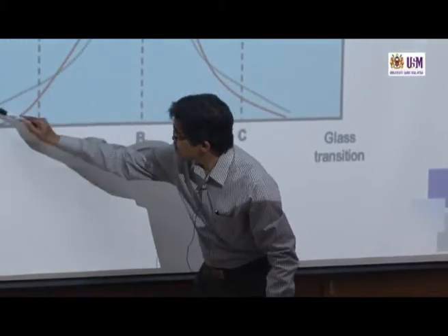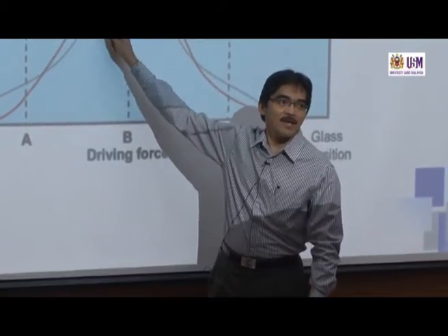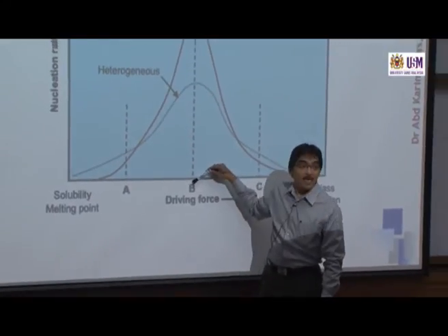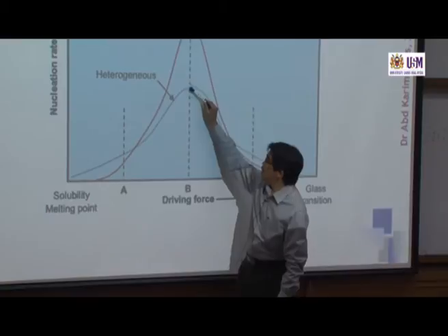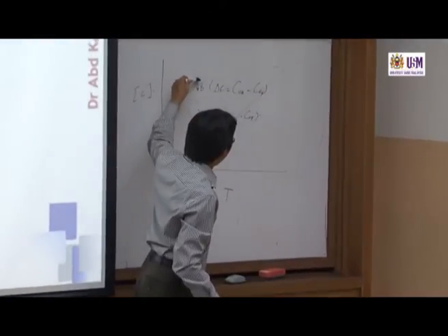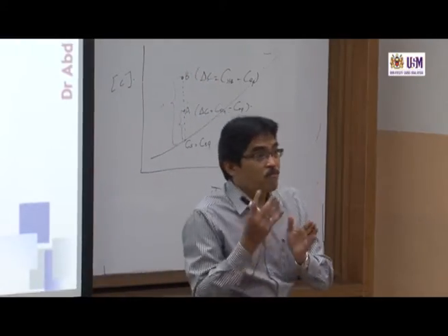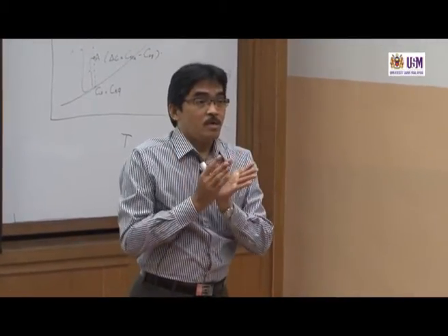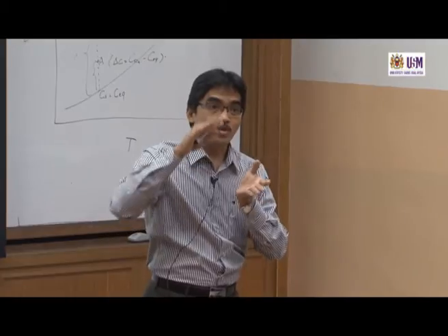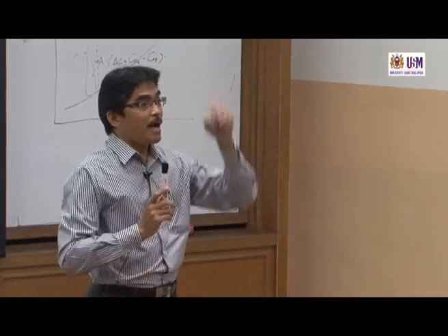So you can see slow and suddenly fast, and reach maximum at point B. So what happened between here until point B? We get the degree of supersaturation getting higher and higher when we remove more solvent by evaporation. So the concentration increases, so the degree of supersaturation also would increase. So you get an increase up to a point.